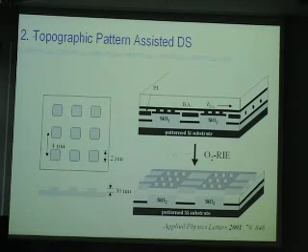So we fabricated a pattern structure using photolithography. As you can see, this one has 2 micron mountains and 4 micron periodicity. If you look at the pattern in this direction, we have a mountain like this. The height of this mountain is about 30 nanometers. We combine this pattern structure with the directional solidification I introduced before. So the idea is when the benzoic acid crystallizes like this, it makes a flat single crystal surface, and we use this topographic pattern structure.